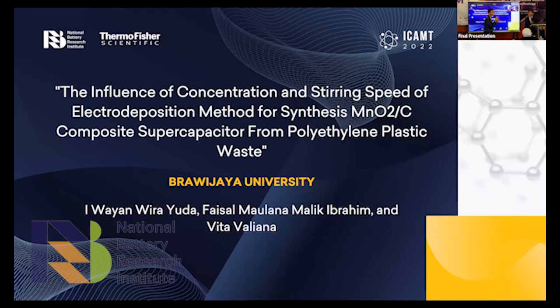So you use the stirrer to combine these materials, to combine and bind strongly the composite. So how long do you find this material can mix homogeneously? Okay. Because we want to mix this homogeneously between manganese dioxide and carbon, with the magnetic stirrer we use a time of 1 hour, and after that, to prevent agglomeration, we use sonication, because after we did the electrodeposition, sometimes it still has agglomeration. So to prevent this, we also did ultrasonication for 1 hour, stirring with various stirring speeds, and after that we do the ultrasonication.